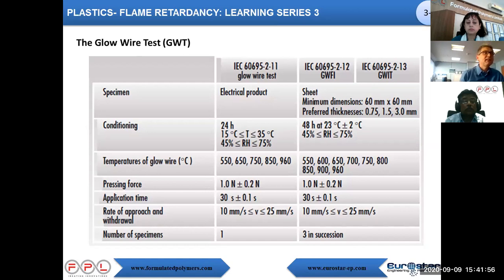The difference is that when you see in the standard that it ends with 11, the test is run on a part. This is a glow wire test. When the test is run on a sample, it can be a glow wire flammability index or ignition temperature. Conditioning is the same as KK explained before for UL. It needs to be conditioned, of course, because some materials, especially some polyamide, pick up moisture. And you can imagine that a material which picked up too much moisture will be less sensitive to fire.